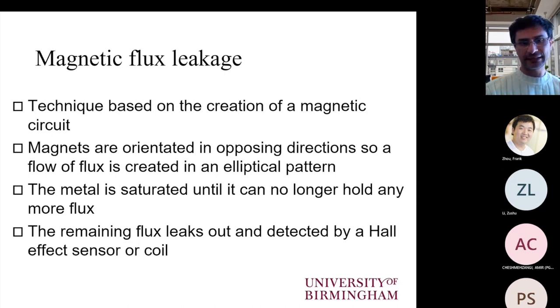So this technique is based on the creation of a magnetic circuit, and that requires very powerful permanent magnets or DC electromagnets in order to enable this method to be applied for the inspection of ferrous materials and ferrous components. The idea behind this technique is the saturation with magnetic flux of the material we want to inspect. In theory, if there is no defect that causes any flux to leak, then we can extrapolate that this material is free of defects, or the defects that it is containing are not severe enough to give a measurable response.